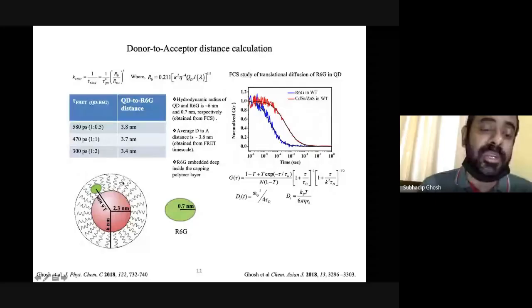So this is fluorescence correlation spectroscopy. From the time measurement, we cannot get the hydrodynamic radius or hydrodynamic size, because it will only give the size of the semiconductor portion, not the capping layer. But if somebody wants to know the entire size, including the capping layer, he should use fluorescence correlation spectroscopy. So fluorescence correlation spectroscopy is a simple method.